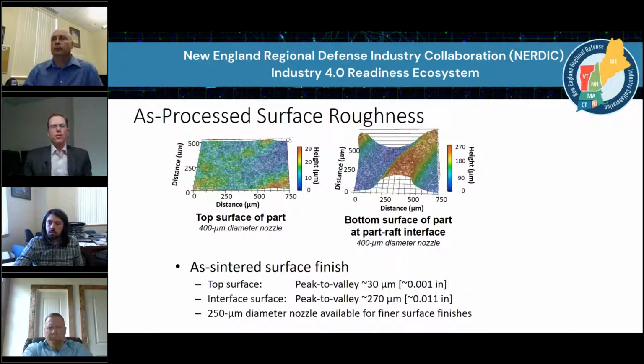If we look at some of the characteristics of the as-sintered part, here we happen to see the surface roughness. On the top surface, it's going to be a little bit smoother than the bottom surface. The bottom surface is intentionally a little bit coarse, a little bit rough, and that's to help with separating the raft from the part. Now, this slide or this image is a little bit old. There's since been just recently an update to the software where it's not quite as rough as shown here.